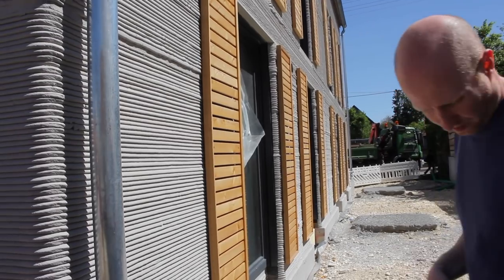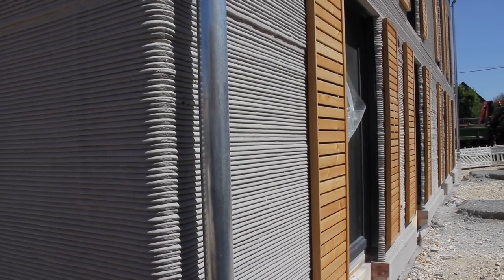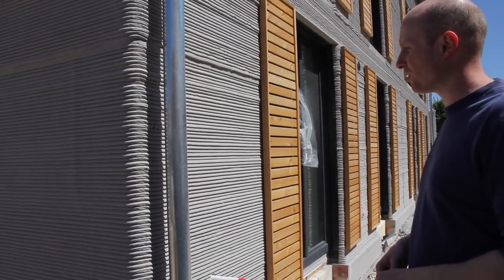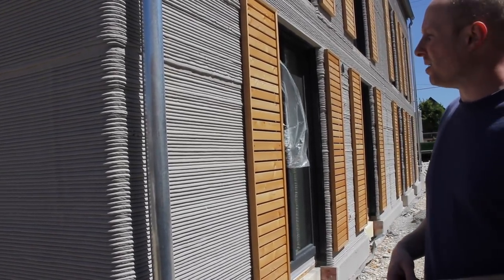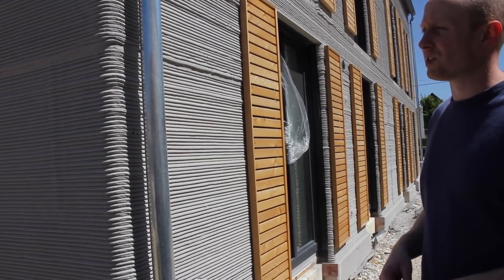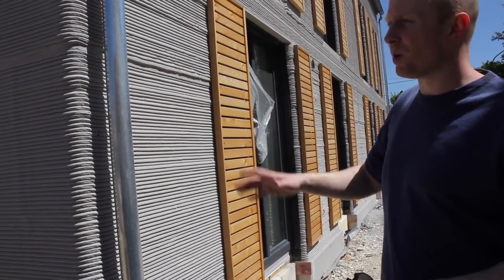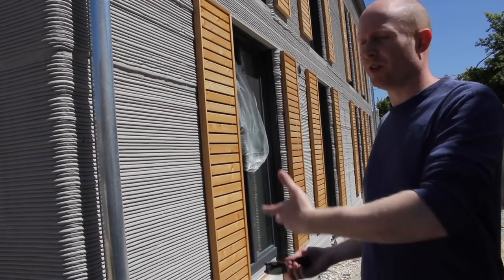These cracks — how can they be prevented? Do you know what caused this crack specifically? In the end it is concrete, so we will definitely have some shrinkage and thermal expansion cracking. I think this will never be quite avoided in the future because concrete as a building material does crack a little bit. As long as these cracks are not structural and the building physics are designed accordingly, it's quite manageable. If you don't want to see them, you can always plaster the building at a later point, like you would normally do with a masonry or concrete structure. The further we go with the technology the better we will be, creating smoother and smoother layers from start to finish.